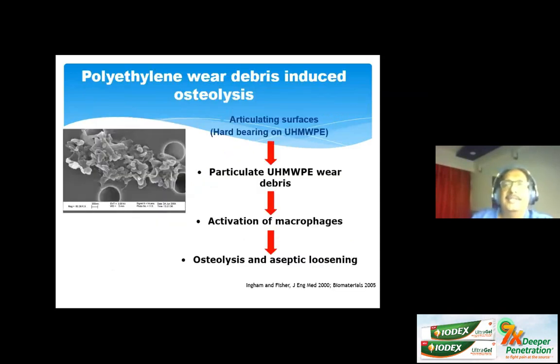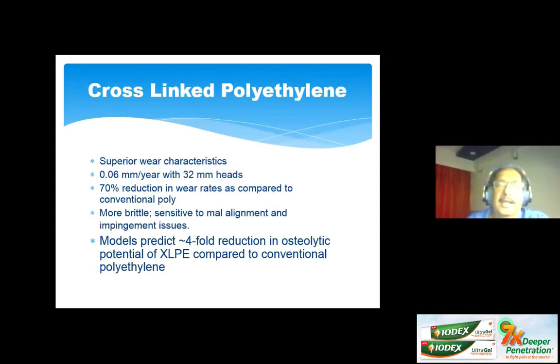So what happens with polyethylene? If you have a hard bearing on a polyethylene, there is particulate polyethylene debris, there's an activation of the macrophages, and there is subsequent osteolysis and aseptic loosening. Now, highly cross-linked polyethylene is what we now use, and that has definitely more benefits compared to what Charnley had available to him. The reduction in wear rates is about 70%.